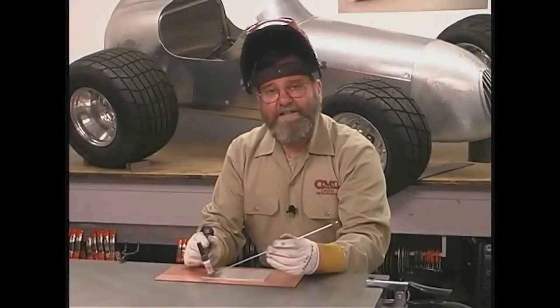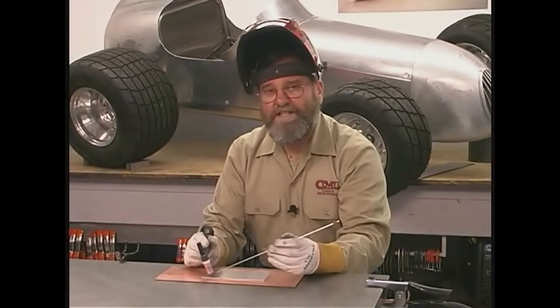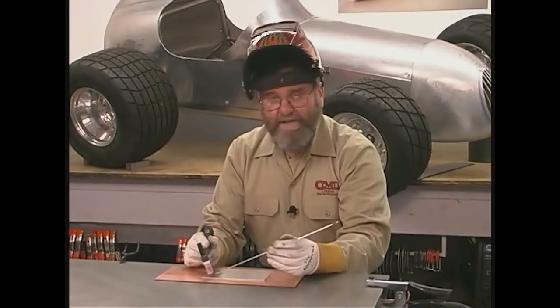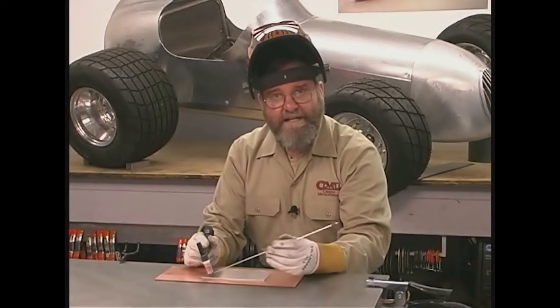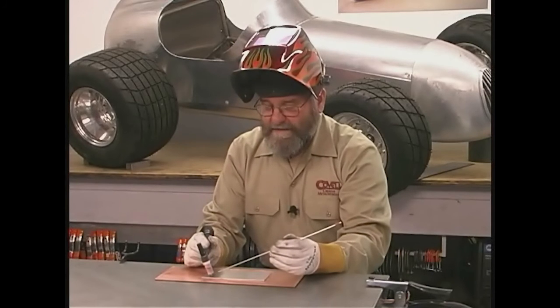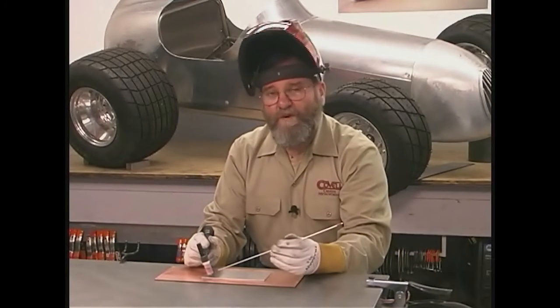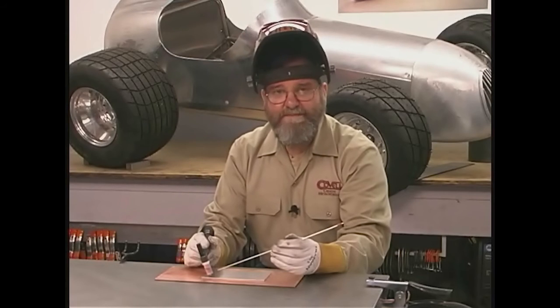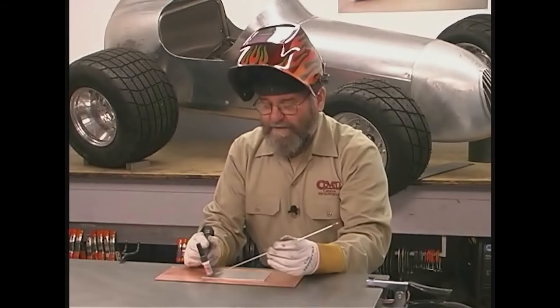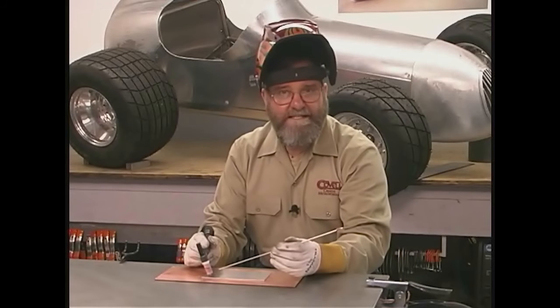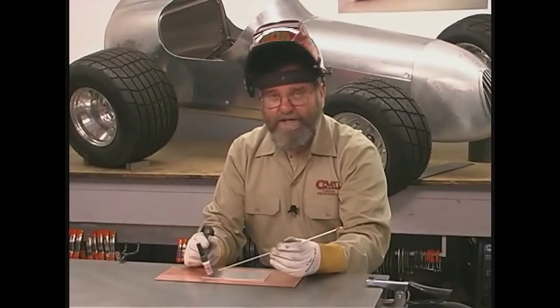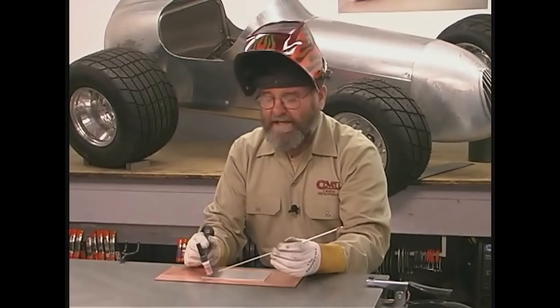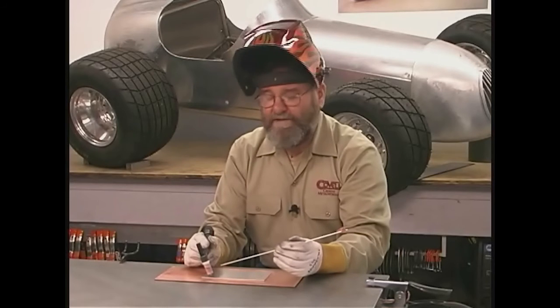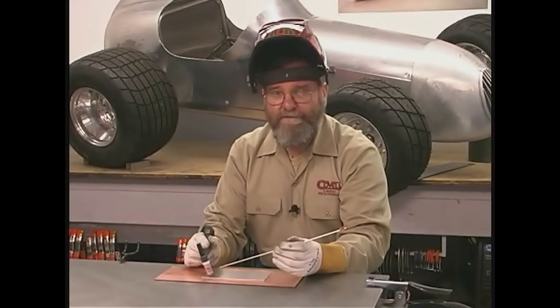I want to talk a little bit about the hand technique used for TIG welding. The first thing we'll look at is the distance between the tungsten electrode and the workpiece. The ideal distance is right about 1/16 of an inch, maybe as much as 1/8 of an inch. If you're holding the tungsten closer than 1/16 of an inch to the weld puddle, you're probably going to dip it frequently, and of course that contaminates the electrode and makes it impossible to weld further.